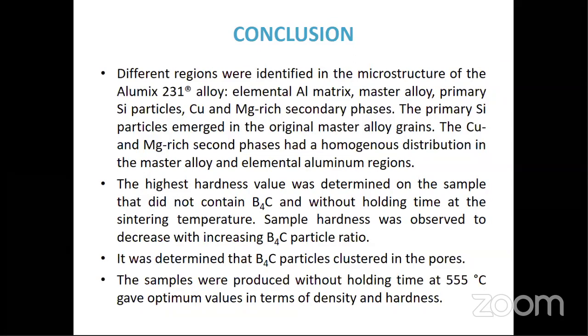Different regions were identified in the microstructure of the Alumix 231 alloy: elemental aluminum matrix, master alloy, primary silicon particles, and copper and magnesium-rich secondary phases. The primary silicon particles emerged in the original master alloy grains. The copper and magnesium-rich second phases had a homogeneous distribution in the master alloy and elemental aluminum regions. The highest hardness value was determined on the sample that didn't contain boron carbide and without holding time at the sintering temperature.